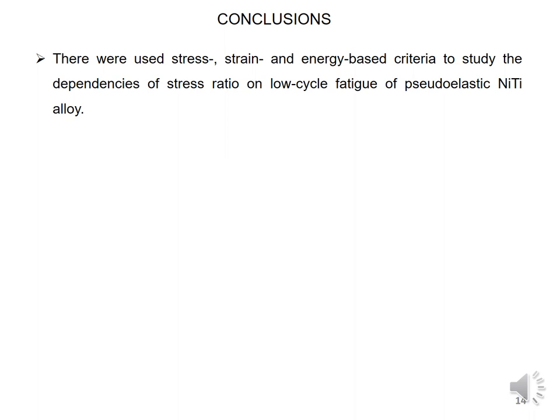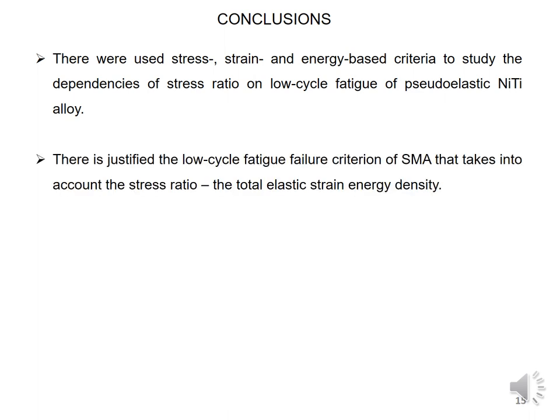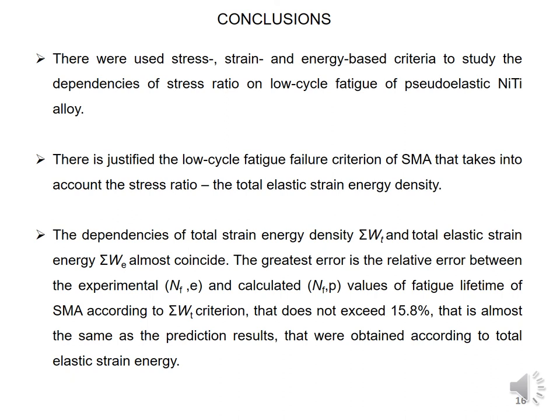Stress, strain, and energy-based criteria were used to study the dependencies of stress ratio on low cycle fatigue of Pseudoelastic NiTi alloy. The low cycle fatigue failure criterion of shape memory alloy that takes into account the stress ratio — the total elastic strain energy density — is justified. The dependencies of total strain energy density and total elastic strain energy almost coincide. The greatest relative error between experimental and calculated values of fatigue lifetime according to the total strain energy density criterion does not exceed 15.8%, which is almost the same as the prediction result obtained according to total elastic strain energy.